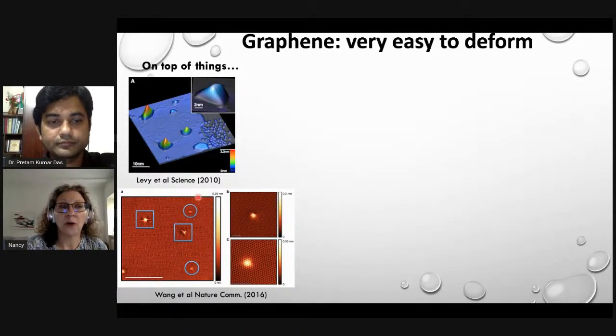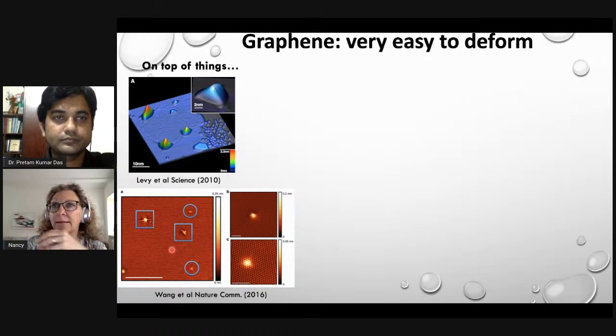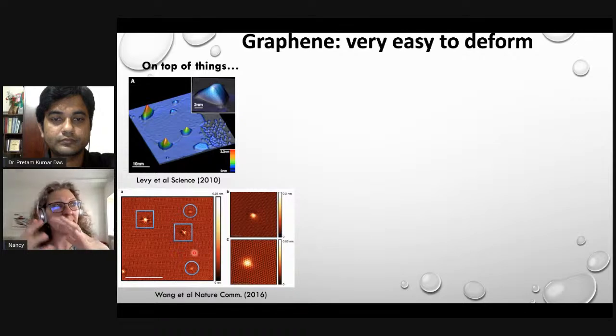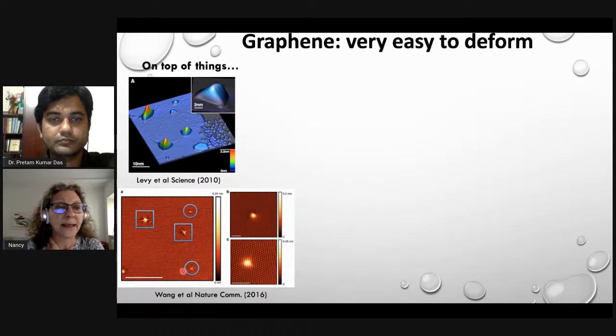In this other experiment, this is basically when graphene is deposited on top of things and impurities or bubbles are captured in the deposition process. Here is when the material is bombarded, damaged with ions, and the substrate reconfigures, and again there is an accumulation of defects that nucleate in local regions and create these particular blisters that again you see have different shapes. That's why they are circles with different formats, but in general have also a triangular type of shape.